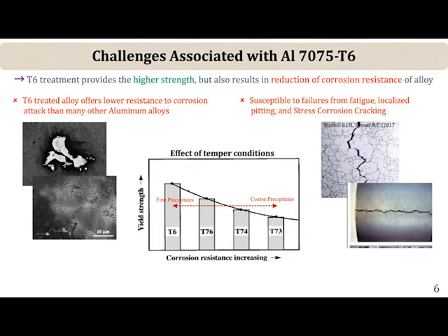And one of the earliest speakers talked about the marine aluminum alloys, where there again is a similar problem in terms of precipitation of the beta phase along grain boundaries, which then leads to depletion of magnesium around the grain boundaries and gives you localized cracking and then exfoliation where entire grains fall off. So this is a problem, not just in the 7000 series, but in a number of aluminum alloys as well. So these larger intermetallics, typically you'll get pitting to occur around them, and then before long, cracks start